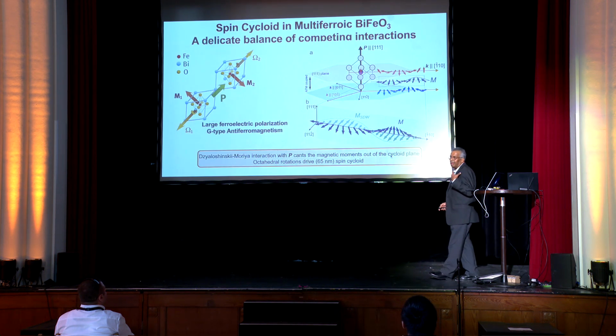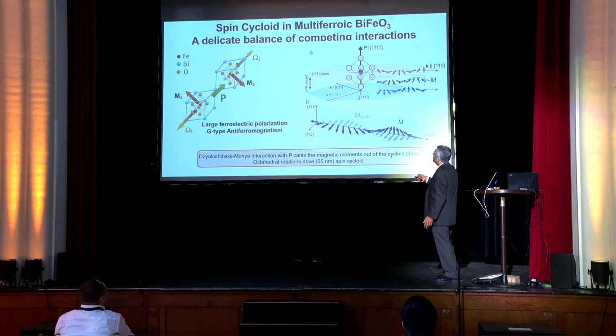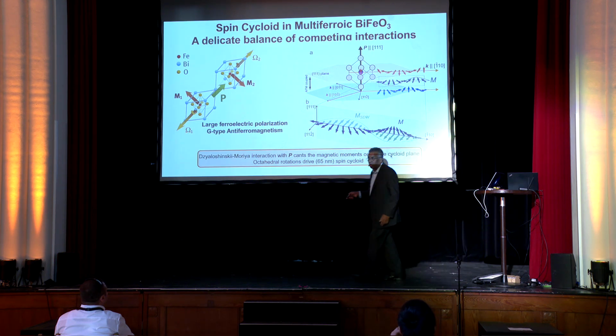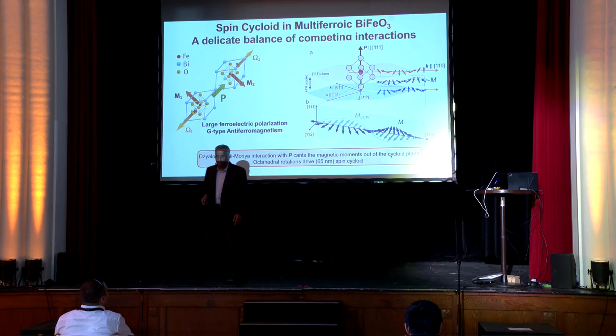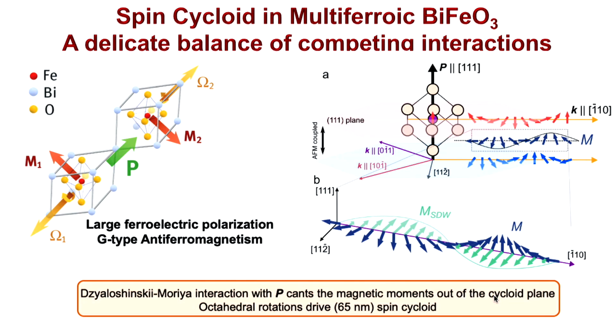Coming to a favorite system for myself, bismuth ferrite, which is a multiferroic material, a very fascinating system from the physics perspective. If you look at it, it's got a very large polarization along the 1-1-1 direction. That's the P vector. It's antiferromagnetic, so you have ferromagnetic planes along the 1-1-1 direction, but which are coupled antiferromagnetically, which is these two vectors.